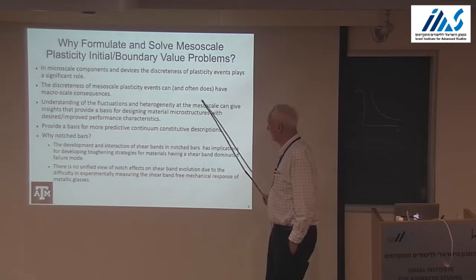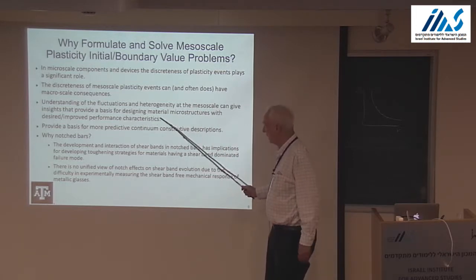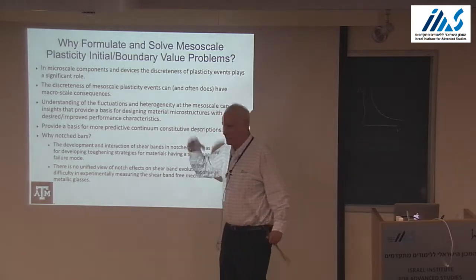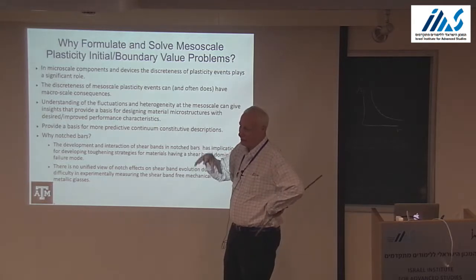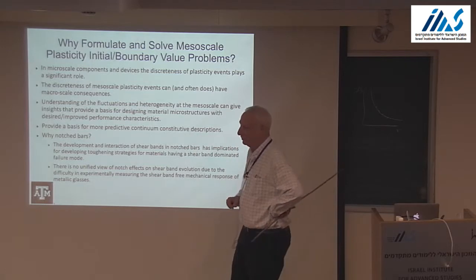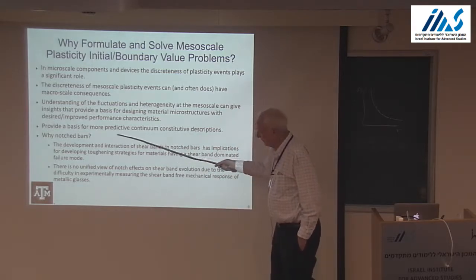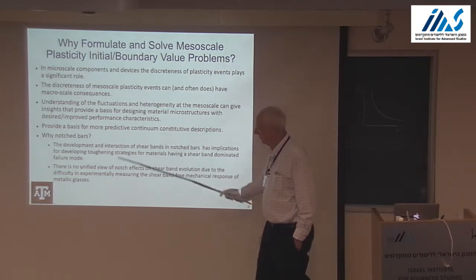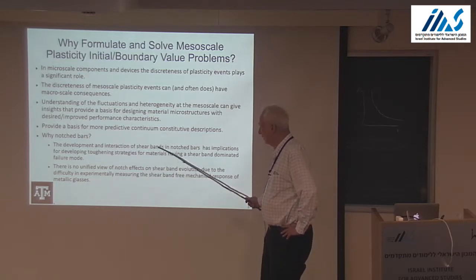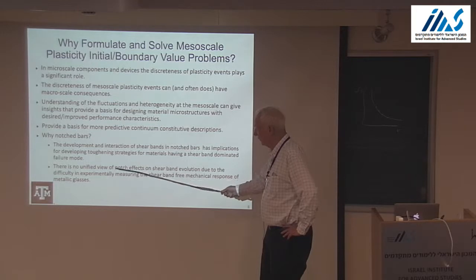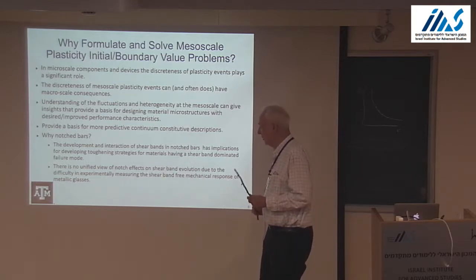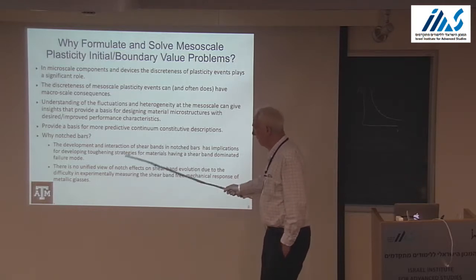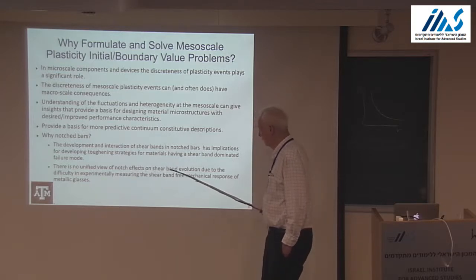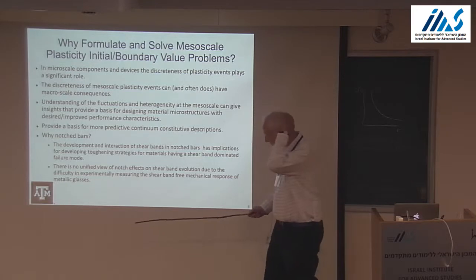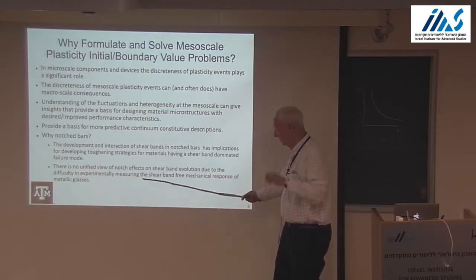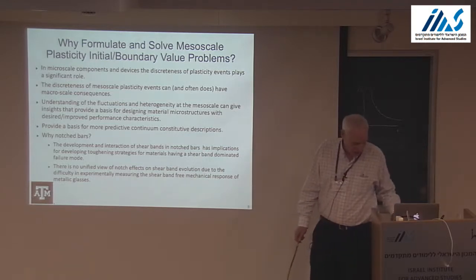Understanding the fluctuations in heterogeneity at this scale can give insight into the basis for designing material microstructures with improved performance. In particular, what we'd like to do for the STZs is look at developing microstructures that can block the shear bands and that can improve ductility. We can hopefully provide a basis for a more predictive continuum constitutive description. For notched bars, the development and interaction of shear bands has implications for developing toughening strategies, because these often involve imposing gradients. There's no unified view of notch effects on shear band evolution. There are a lot of experiments, I'll quote some later, that give very different results on the effect of notches, and we'll see if we can rationalize them.